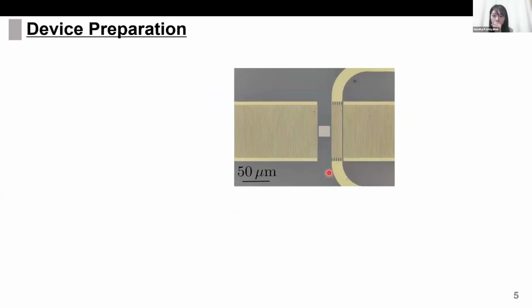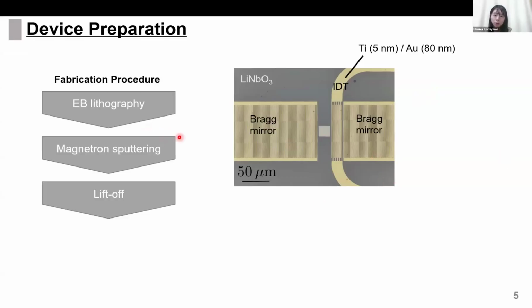Here is an optical microscope image of the device. The substrate is lithium niobate, which has a piezoelectric effect and is typically used in surface acoustic wave devices. The yellow part is made of 5 nanometers titanium and 80 nanometers gold. It consists of an electrode that excites surface acoustic waves, or IDT, and a Bragg mirror that confines surface acoustic waves. This surface acoustic wave resonator was fabricated by applying EB lithography, magnetron sputtering, and liftoff. From electrical measurement, we confirmed that this device had a resonance frequency of around 800 MHz. Using the same fabrication process, we deposited 15 nanometers nickel and 2 nanometers tantalum on a surface acoustic wave resonator.